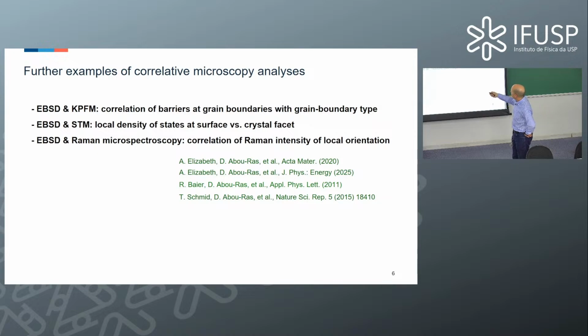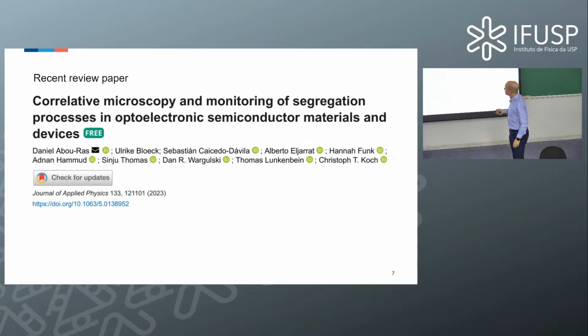And this work here gives details about combining EBSD with Raman microspectroscopy, and it shows that you can use Raman because the Raman intensity depends on the crystal orientation. So you can use Raman as a mapping tool to map local orientations of grains. This is quite interesting, and you can do that down to roughly the diffraction limit of light, roughly 300, 400, 500 nanometers. If you want to read about this in an overview, this is a review paper we published two years ago, giving various examples and also some information about the specimen preparation that we use for these specimens.